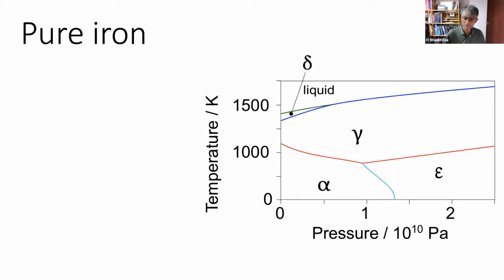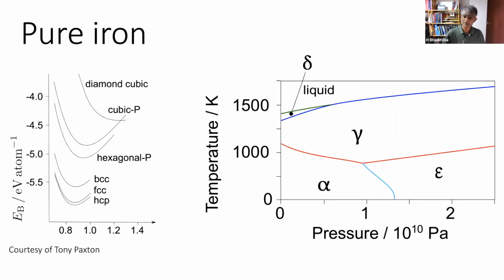Okay, so if we do a first principles calculation to see which is the most stable allotrope, and you ignore the magnetism, then the ground state would be hexagonal close-packed, not body-centered cubic. Now, just imagine a world in which we had iron as a hexagonal close-packed material. It would be very painful because hexagonal close-packed systems in general have much fewer slip systems than the cubic forms of iron. And therefore, we would not have the civilization that we know. You owe the civilization to the magnetic properties of iron.